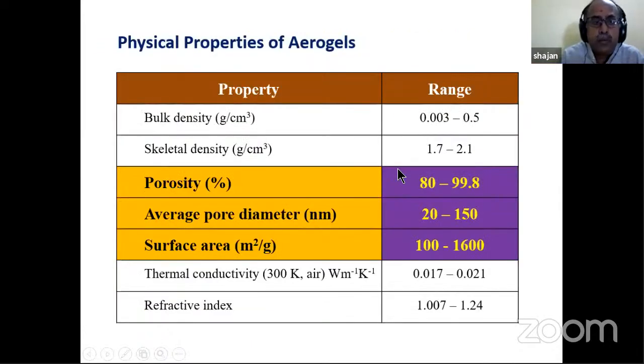And if you see the physical properties of these aerogels, as I said, it has a very low density, and the skeletal density is also very low. And we see the porosity is almost 80 to 99%, it is completely porous, so that it can absorb anything. And the average pore diameter you can have is 20 to 150, and you can tune the surface area as well as the pore diameter. All these are reported in the literature, and its thermal conductivity is very low. That is why it can be used as an insulating material.